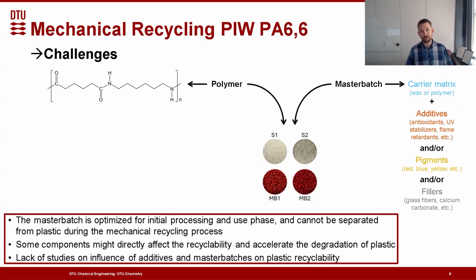And one of the problems here is that if there's any adverse combination of the additives that comes from the base polymer or from the master batch, we would have a risk of an acceleration of the phenomena happening in the system. And this is some of what we've observed for some of these systems. And there are not many studies on these combinations of additives. So this is actually a common way of operating in industry, that you would combine a different resin provider with a given master batch, under the assumption that this would actually not be important for the use of the material itself.